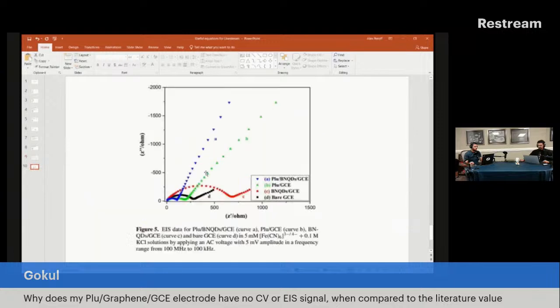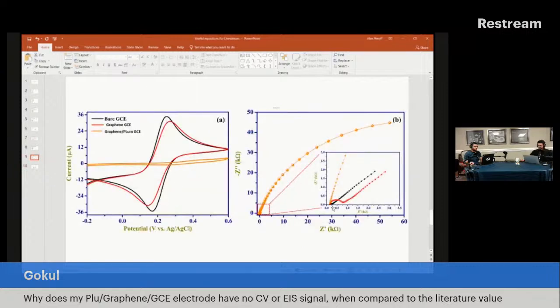Now he's saying, if we move on, he showed this image from the literature. He's just trying to reproduce a literature study, which is perfectly normal. We all try to do that, especially when we are in graduate school. And he's trying to reproduce these Nyquist plots, or at least see a similar trend in terms of getting these semicircles and a diffusional tail. So what he's really trying to determine is, why is he not getting the blue Nyquist plot? Why is he not getting a small charge transfer resistance and then a diffusional tail? He's getting nothing. He's just getting a straight line.